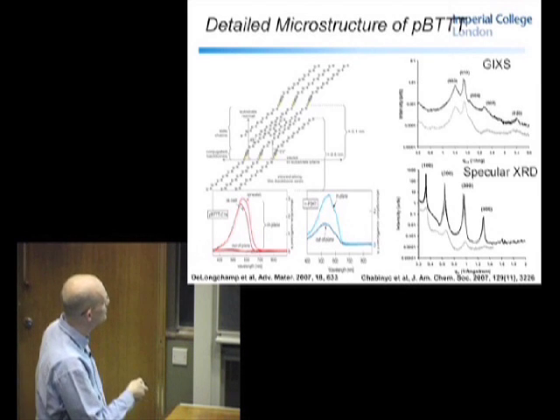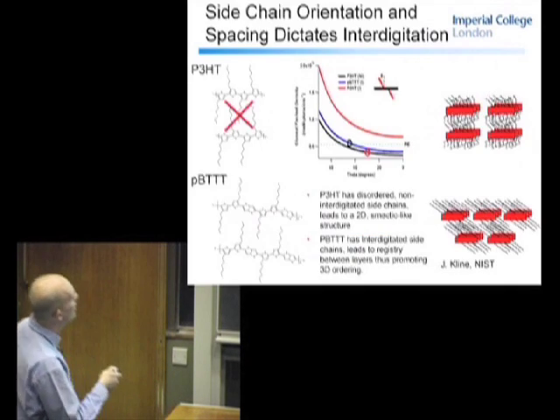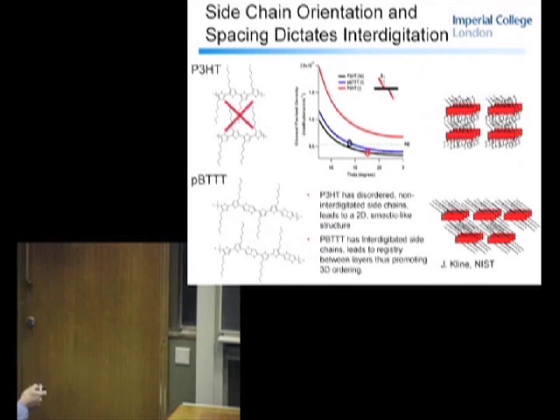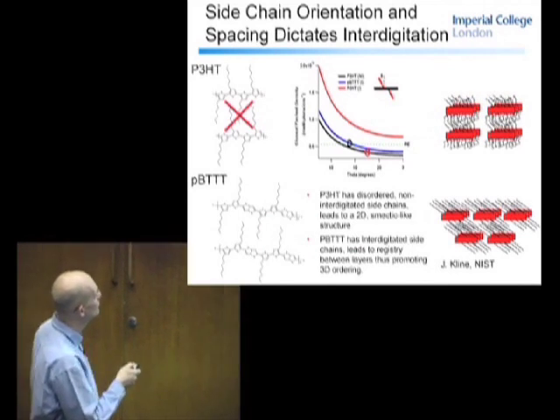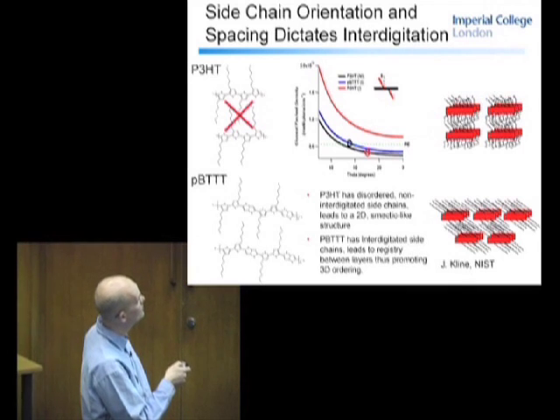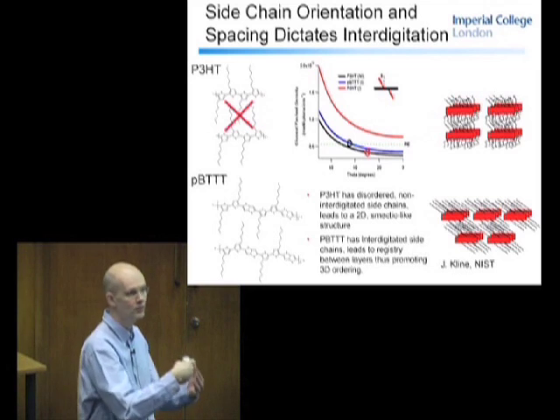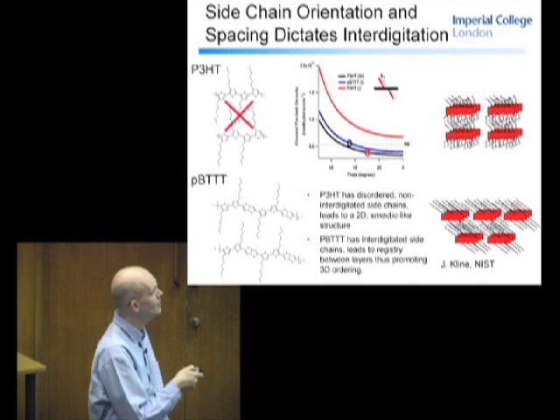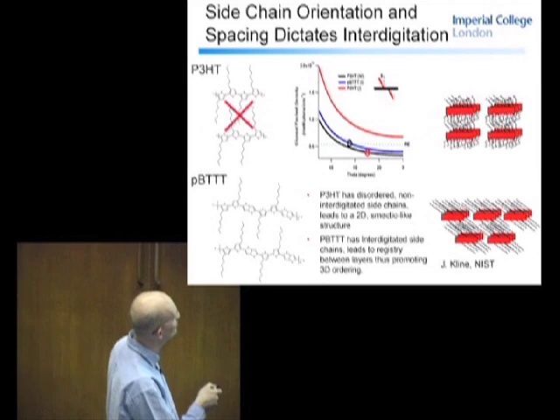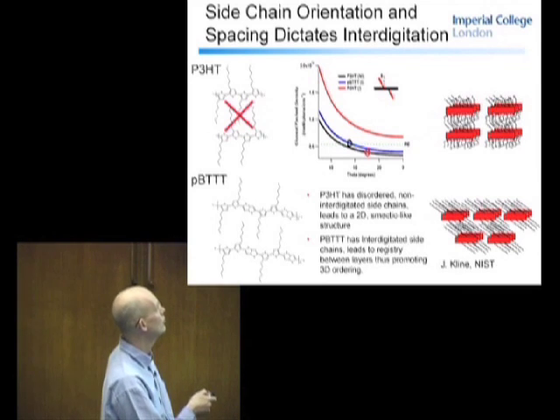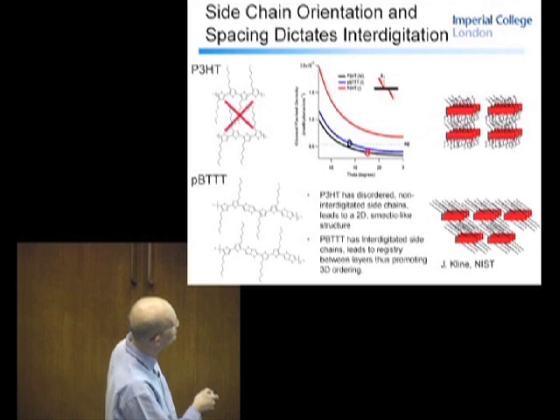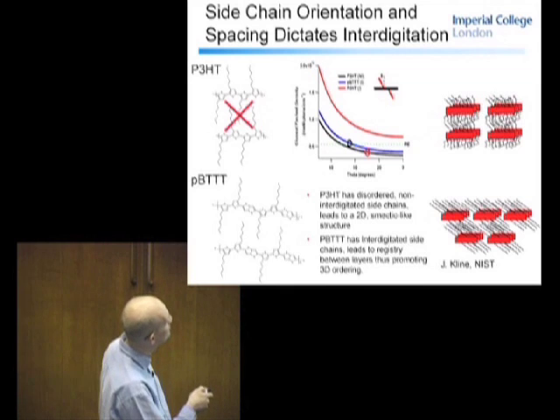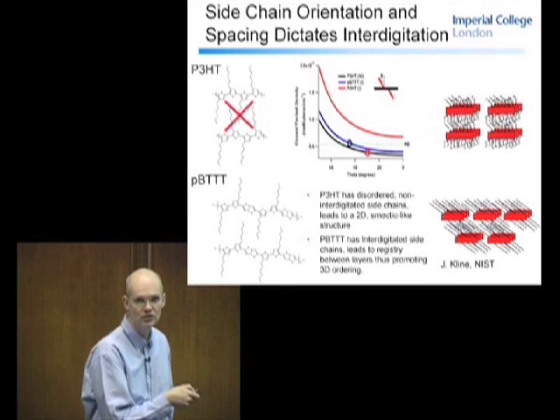And there's been some publications. This is quite a nice one from the NIST group, 2007, Advanced Materials. And what people are starting to discover is that this whole order and organisation is really dictated by the side chain interdigitation between the lamella. And in the case of P3HT, it had never been done before, but if you just do a very simple calculation of the sort of close packed density that these alkyl chains would need to have if they were interdigitated, depending on the angle that they project from the main chain, and you assume a D spacing because you know that from X-ray studies.